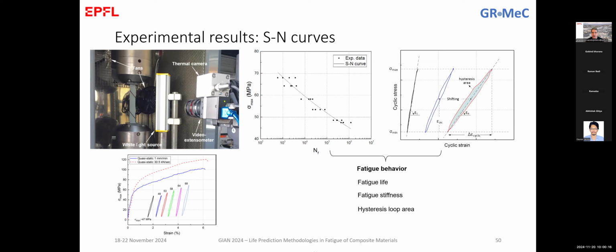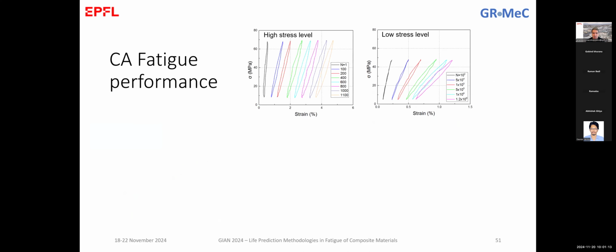Another point that is very significant here: you see that we use different equipment for different measurements, and at the end we want to put them all together and draw curves. What is very significant, and we've seen in the past that it was causing a lot of problems, is the synchronization of all these measuring devices. If you measure load with the machine and your strain with the video extensometer camera, and they're not synchronized, and the camera gives you a strain value that does not correspond to the stress at the same time interval, then all the results will be falsified. So all these parameters have to be confirmed during preliminary experimental programs before even going into the full experimental campaign. So here are the first results.